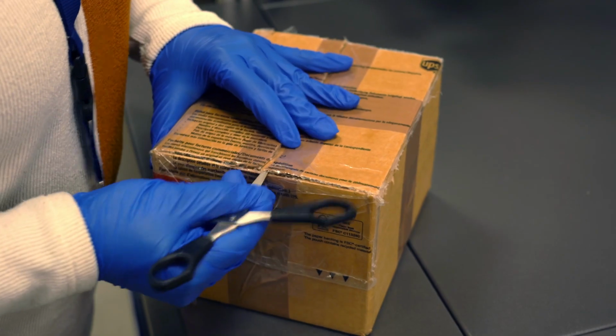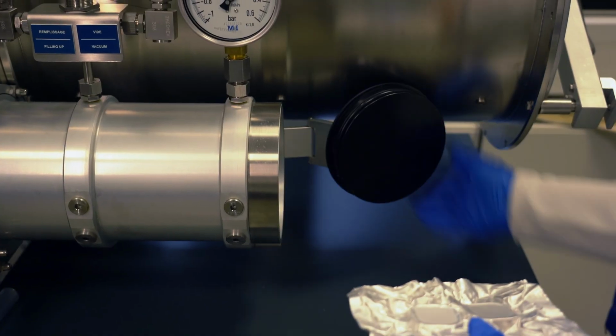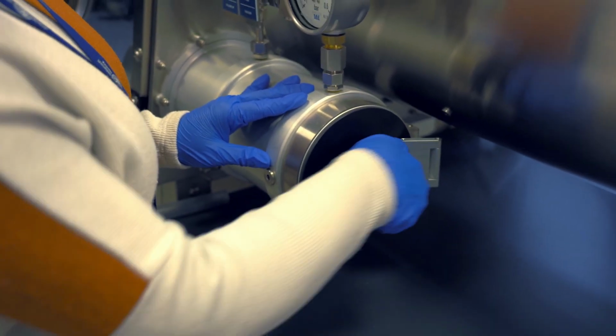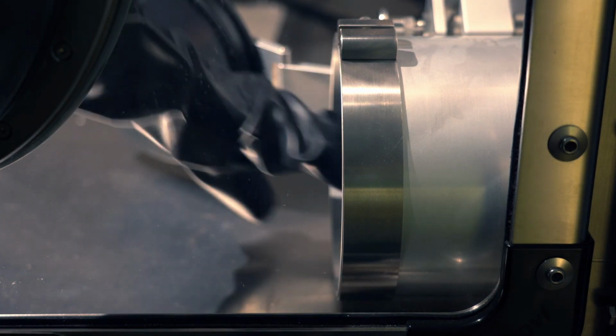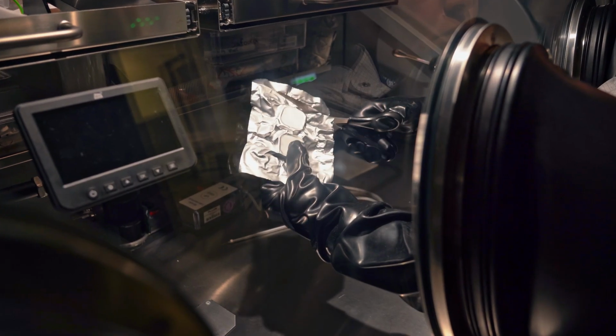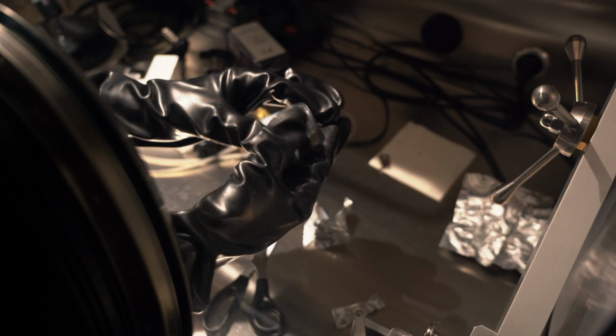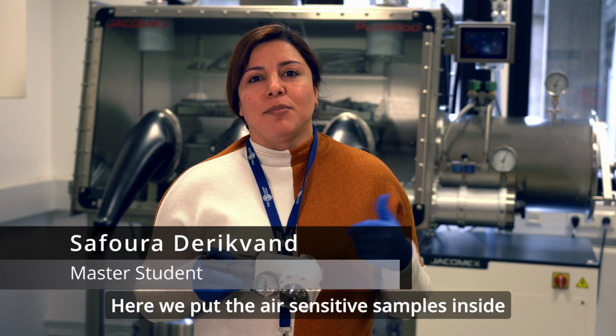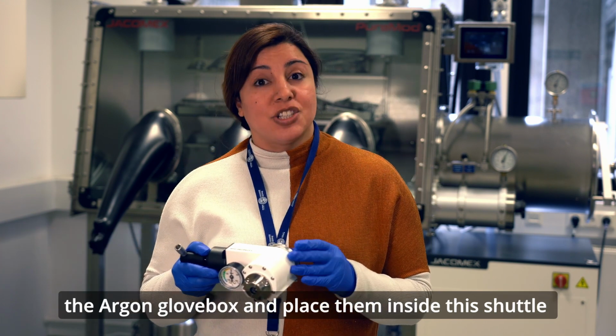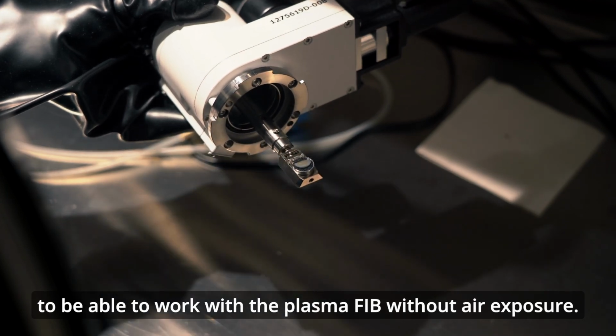First of all, we got new samples. Here we put the air-sensitive sample inside the argon glove box and place it inside this shuttle to be able to work with the plasma FIB without air exposure.